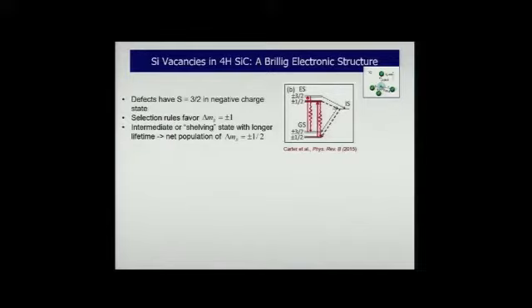Just why are these defects interesting, and what makes a whole class of defects interesting? Part of it, without going into too much detail, let me just show you what's believed to be the electronic structure of the negatively charged silicon vacancy in silicon carbide. Some of this is known, some of it is surmised, and some of it has to be validated further. But these negatively charged silicon vacancies have a net spin 3/2, which means that they have states or projections of plus or minus 3/2, plus or minus 1/2. So the ground electronic state has the two spin states, plus or minus 1/2, plus or minus 3/2, and also the excited state.